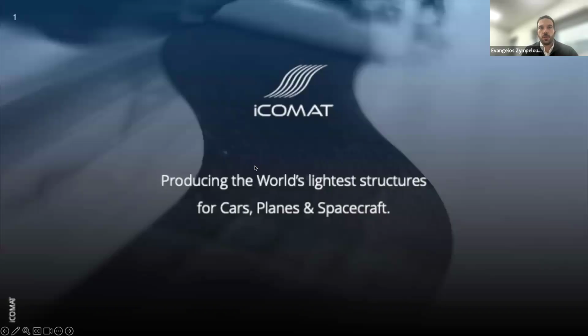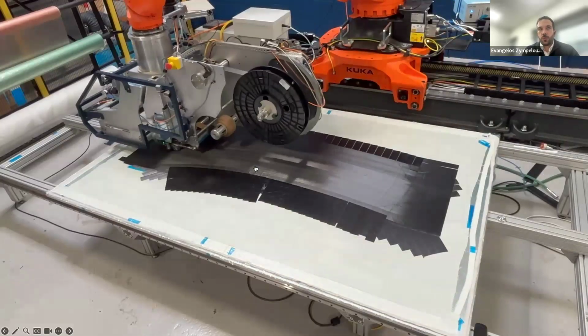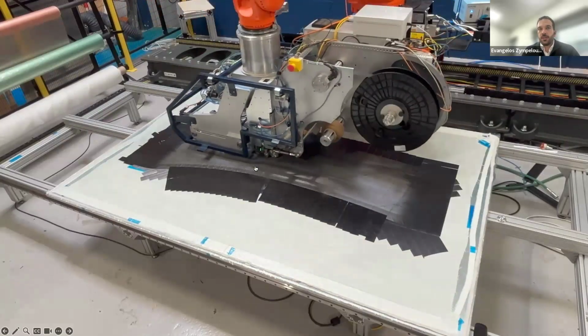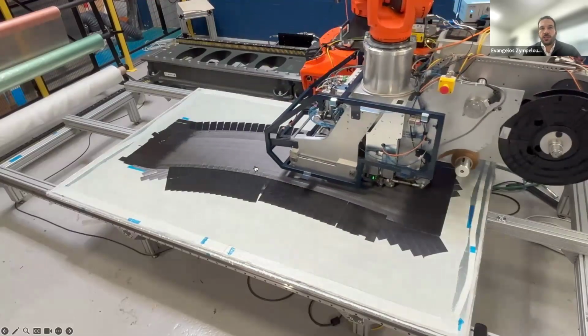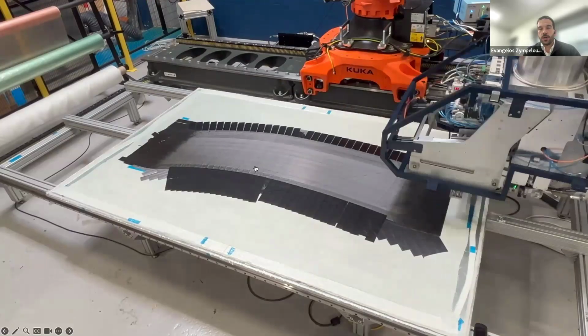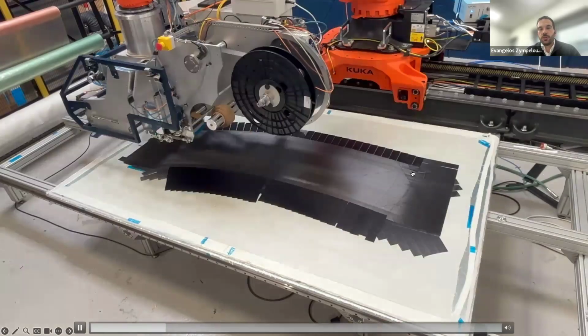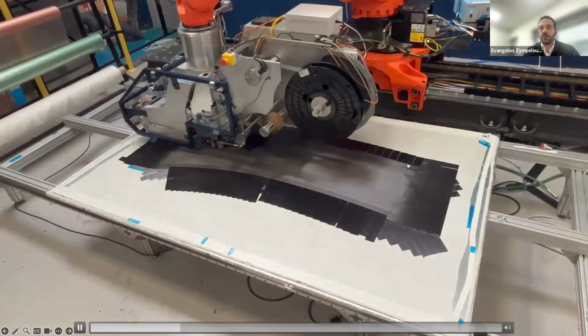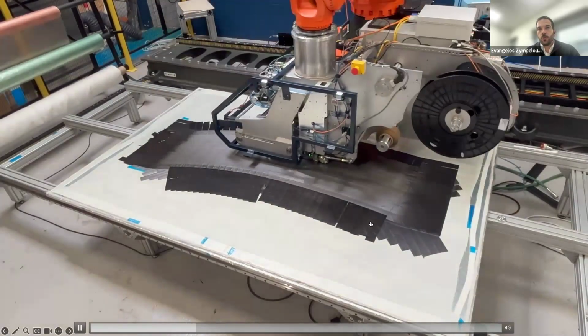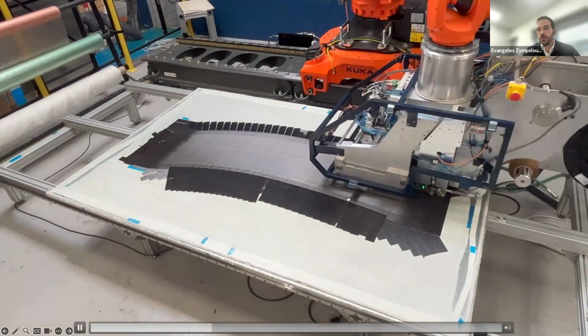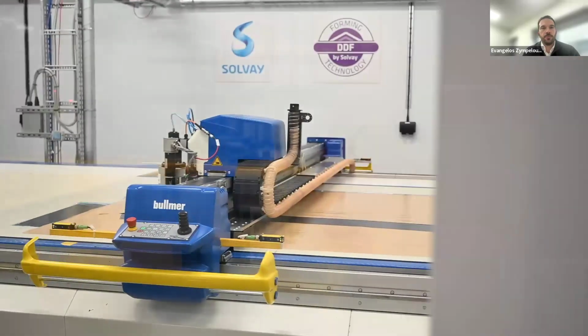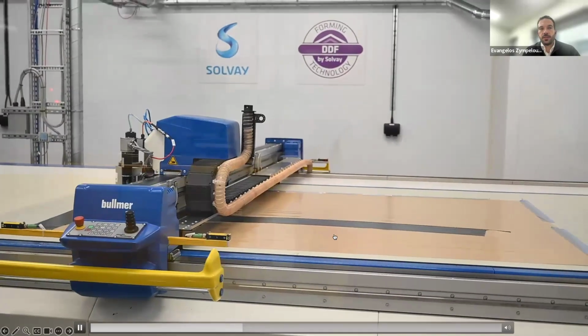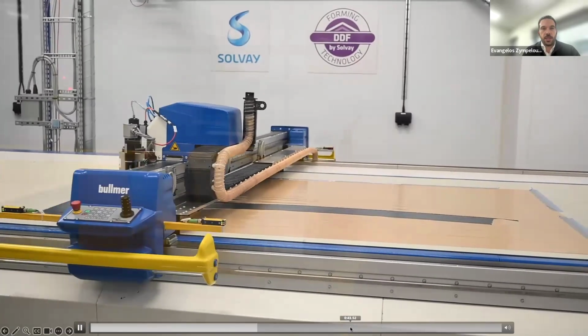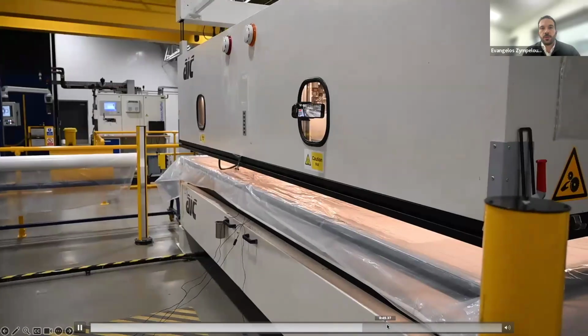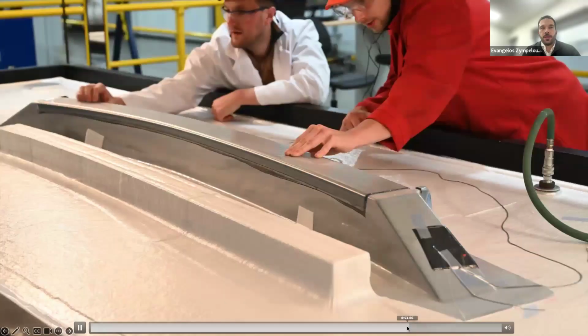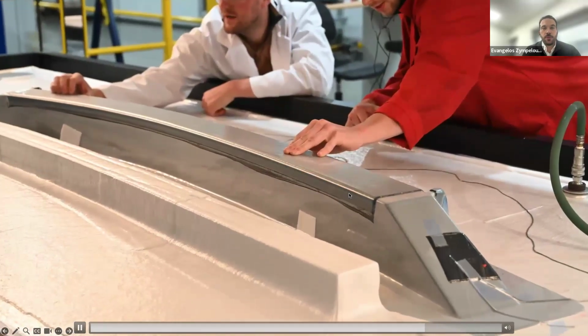So once we do this, then we use our CAM software and we program the machine, and then we let it run. And in this case, it did about 21 layers all in one go. And also what you will notice is that we have nested multiple frames together. So this preform here can do about 3 fuselage frames. Then we ply cut the preform, and then in this case, we use the hot drape forming system. And the result is a defect-free beam that you see here.